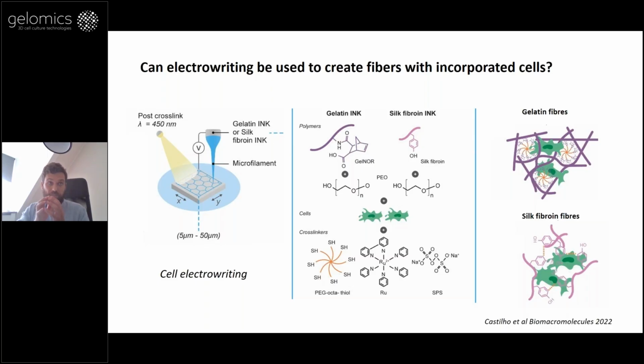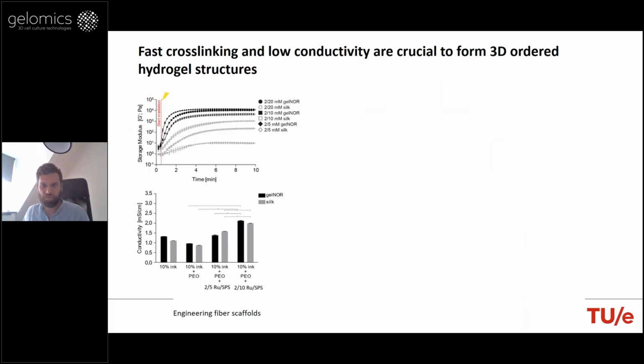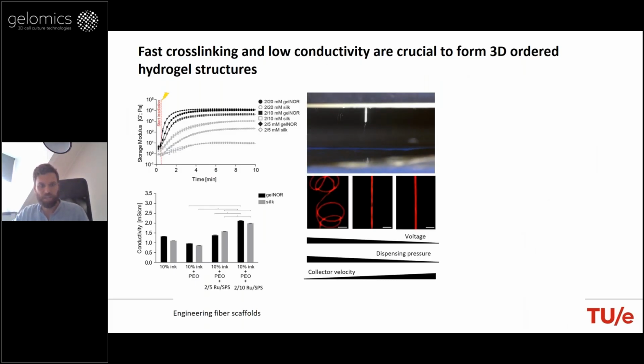So the hydrogel filament crosslinks and solidifies immediately, and it's not drying out, because that will lead to low cell viability. We combine it and explore the use of two components for the initiator system, in this case ruthenium and sodium persulfate. What was very interesting to see was that the two different hydrogel combinations allowed us to achieve the rheological properties, in this case the viscosity and the speed of crosslinking, that we needed for creating a stable jet. And the addition of PEO was also crucial here to achieve the essential viscosity.